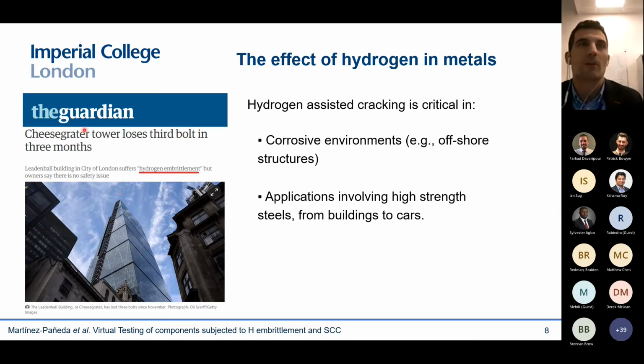You can see an example here. This is a famous newspaper in the UK. This is one of the most famous skyscrapers in London, and you can see that the newspaper reports these hydrogen embrittlement issues. And as you see, this happens in very inert environments. We don't need to be surrounded by H2S anymore. The water vapor is enough to trigger hydrogen-assisted failures.